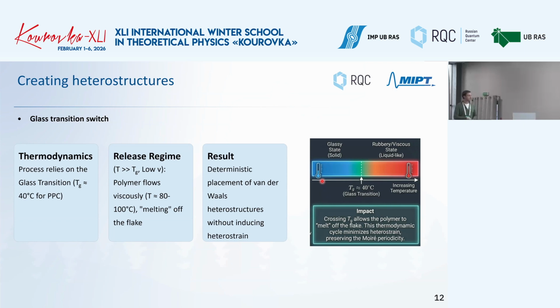Yeah, so quite easy. There are three processes. First, there is thermodynamics. The process relies on the glass transition. Then you need to release with this slow speed of detaching and temperatures. And then with this, you can deterministically place your 2D material on top of another thing in the place where you want. Then you repeat this many times, and you can make a stack of different layers.